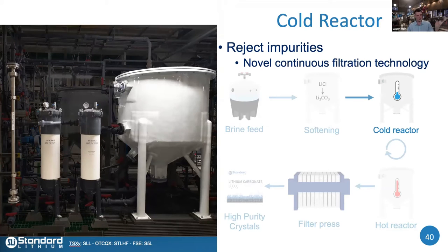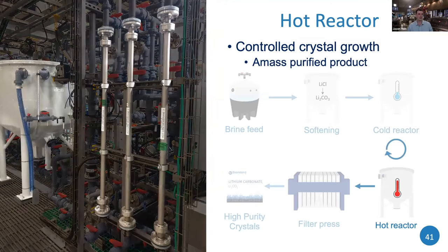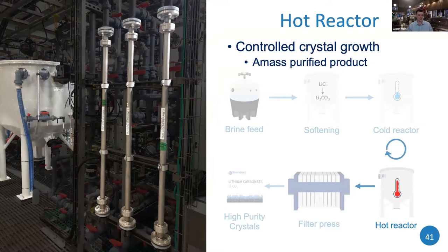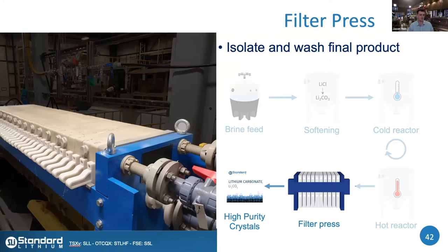And then a duplicate of this is over on the hot side, where the crystals are growing in this hot reactor. And then once again, being filtered against the ceramic membrane chain to get us our isolated compounds. Those are then carried through from a thickened slurry into our filter press, which are then washed and dried to get us our final material.